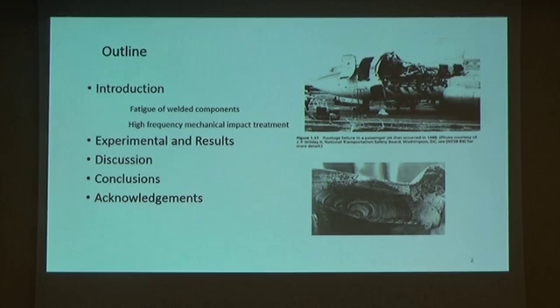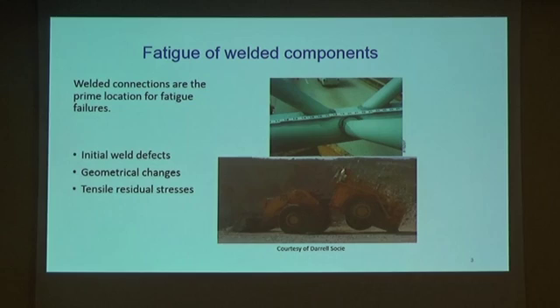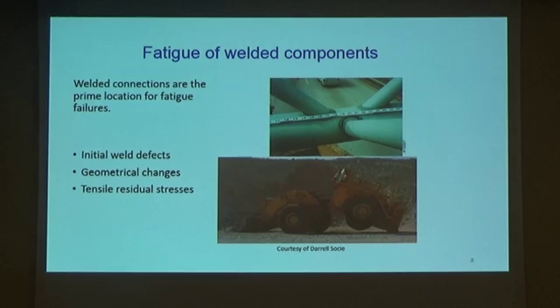Welded connections are always the prime location for fatigue failure. Why? Because of three main reasons. The first is that we always have welding defects. Second, we have geometrical changes because of the weld profile. This induces a high stress concentration factor and consequently decreases the fatigue strength.